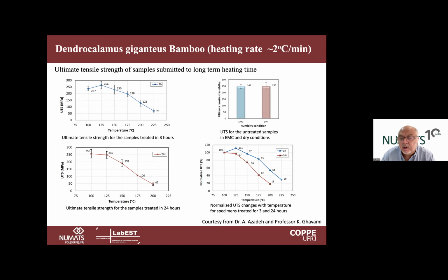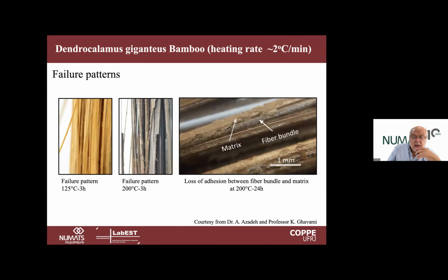When we leave it for a longer time, we lose even more strength. This is mainly because of the decomposition of the material, as the filaments are not together anymore, so the stress transfer cannot be made. So the material works like this: when we break one filament, one fiber of bamboo, then the process of fracture starts. That's the main mechanism of the failure pattern. So this is the loss of the adhesion materials between the filaments of the fiber bundle of bamboo.